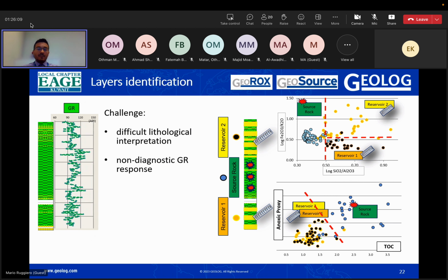actually three different regions. The top and the bottom part are two reservoirs with much more abundance of silicon over aluminum, which is a marker for sandstones versus clays. And also the presence of higher TOC and higher uranium proxies and molybdenum, which are anoxic proxies that can help us to detect the source rock in the middle.